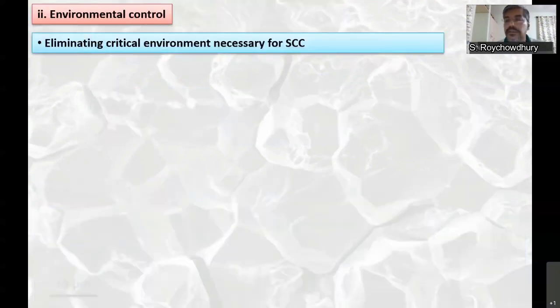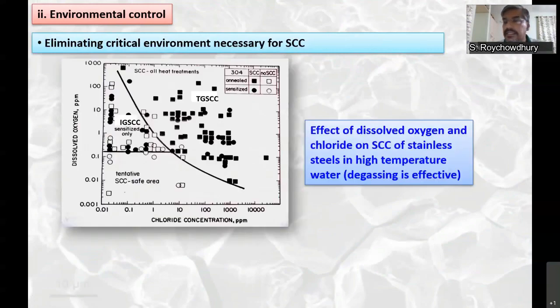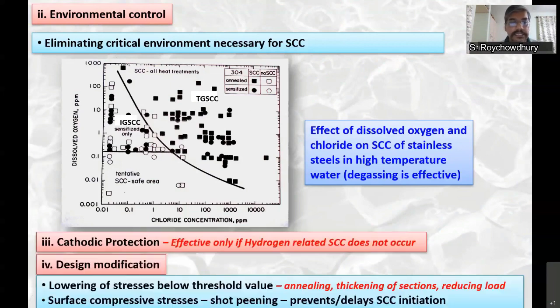Some environmental control steps that you can do: eliminate the critical environment necessary for SCC. As this figure shows, the combination of dissolved oxygen and chloride concentration is very important. So this is the SCC safe area. If you have low dissolved oxygen levels, totally deaerated, very, very low dissolved oxygen, then you can tolerate a higher concentration of chloride without occurrences of TGSCC. But if the dissolved oxygen is high, then you cannot tolerate a very high concentration. The chloride concentration has to be very low, meaning the water purity has to be very good for SCC resistance.